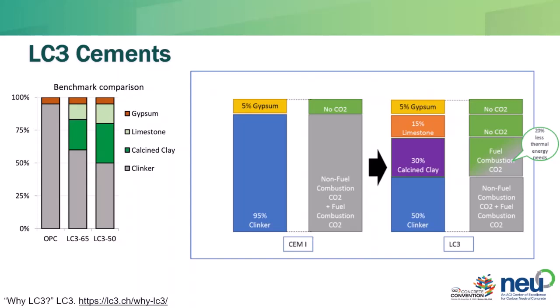You can't see my mouse, right? Yeah. Okay. So on the left, Portland cement, right, and then she's saying let's put in some limestone and calcined clay to replace that, either at a 50% or a 35% replacement level. So on the right here, you can see putting in the limestone, there's no CO2 emitted. Putting in the calcined clay does need to be heated, but not as hot as Portland cement, right? And so you have a lot less emissions, and so that's really taking off.